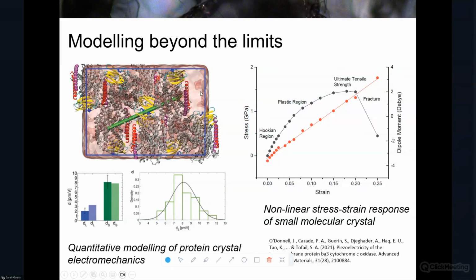But the biggest thing we've ever run is this protein here. We get excellent matching for both longitudinal and shear piezoelectricity versus PFM measurements, which is an AFM technique to measure piezoelectricity. And what we've been developing more recently, as I mentioned, is this in silico stress strain curve, where again, once we have an XRD structure, high resolution XRD structure, we can fully predict using static, low computational expense calculations, the full dynamic stress strain curve of a molecular crystal.